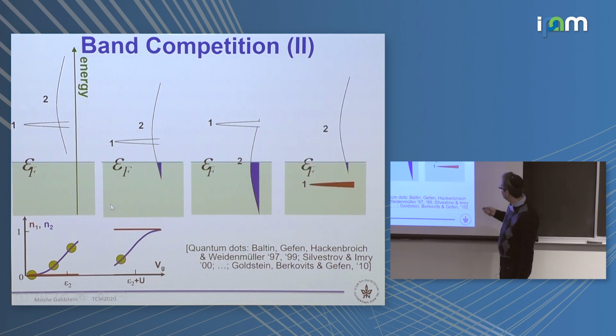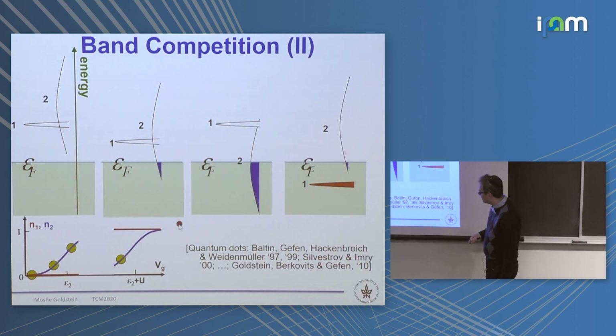Now let's say that I start from the other limit. Suppose I went to extremely high gate voltage, I filled in both bands, and now I start decreasing the gate voltage and start emptying them. So the first band to get depopulated is again band number 2, again because it has this tail in density of states. So this is what I'm going to have on this side. And the only way to reconcile those two limits is that somewhere in the middle, I started filling in band number 2, then I regretted, then I filled in band number 1 and took the electrons out of band number 2, and then filled band number 2 again. So the total density is monotonic. I haven't broken that, but the distribution between the bands is not monotonic.